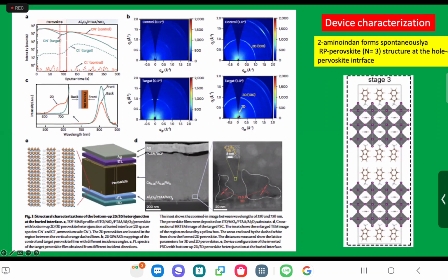There's some evidence. We can see, when we take the GIWAXS at a wider angle, the 2D layer formed. But if you take it at a narrow angle, where we mainly probe the surface of the perovskite, we don't see it. So it's buried. It's a buried junction. The 2D layer actually forms at the bottom of the perovskite, in contact with the HTL. The luminescence shows that too: if we take it from the bottom side, we can see the luminescence and the absorption. However, from the top, you cannot.